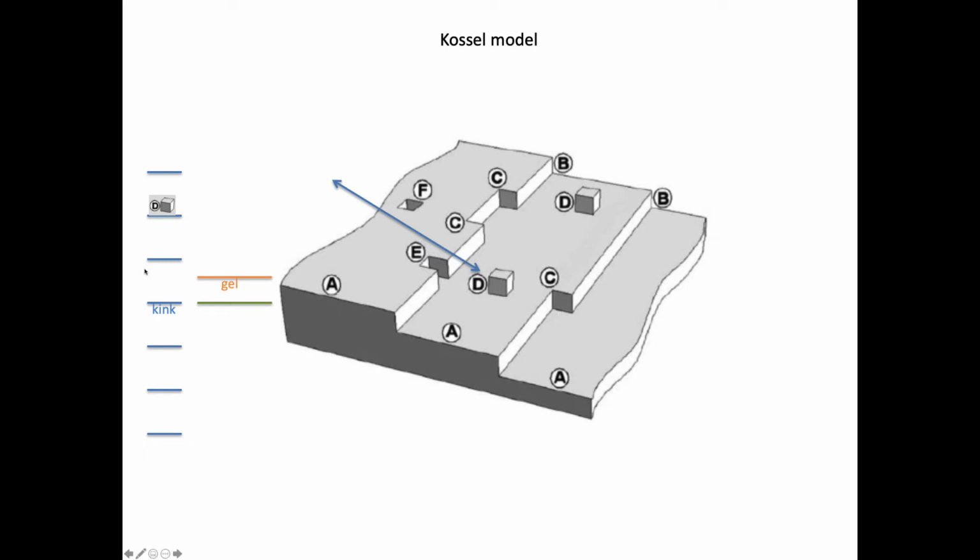That will be entering one of these higher energy levels up here, and consequently the most likely fate of this particular component will be to jump back out into the gel, into the lower energy state. So anything that grows will just keep on coming back out into the gel phase.